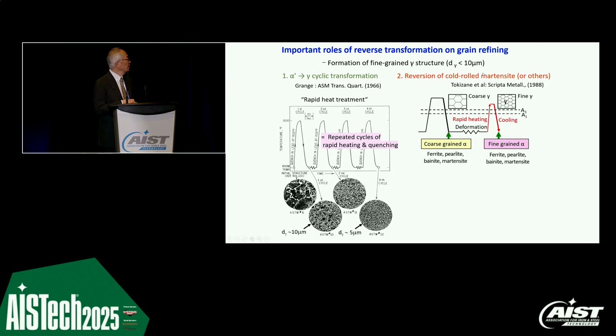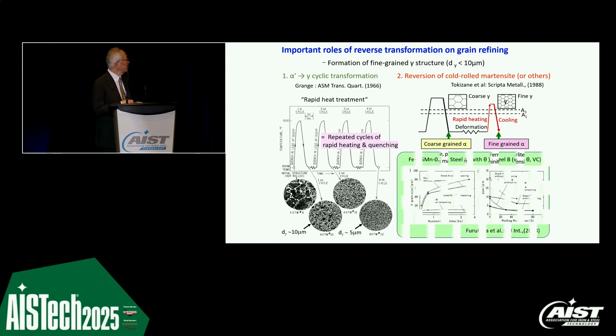The other case, in the 80s in Japan, Professor Tokizane applied cold rolling and reversion of the martensite. By doing that, we can reduce the austenite grain size down to 5 micron, and by having particle pinning, maybe 2 micron or so. We also applied that in this case for model steel.